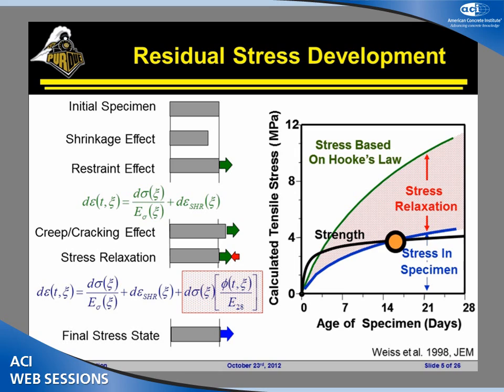However, there's an additional effect that comes into this, which is really beneficial at early ages, and this is viscoelasticity. This is relaxation. This is stresses that are being worked out of the system at very early ages. So you can see that the stresses are substantially reduced by this viscoelasticity. Now, I think that this is a really important point to bring out here, because in this particular case, viscoelasticity is helpful to the system. Creep, for example, relaxation is a good thing because it helps to reduce the stresses in the system.